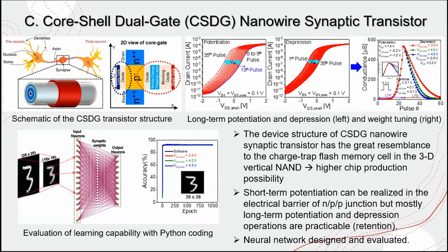Core-shell dual gate is another synaptic transistor based on a novel device structure. What we can expect better from this device is that the device fabrication and structure are quite similar to the flash memory cell that is commercialized these days. You may have heard of VNAND, vertical NAND. Vertical NAND is based on a cylindrical structure and a nanowire based flash memory cell. You drill a hole very deep, penetrating numerous multilayers of metal gate and dielectric, penetrating all the layers simultaneously.